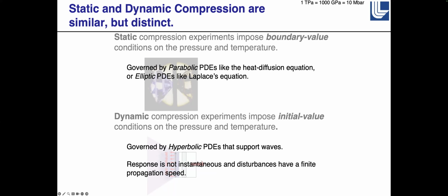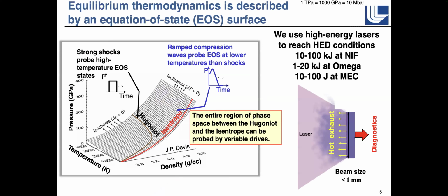So if you think about that, the types of partial differential equations that describe those, parabolic differential equations like the heat diffusion equation, are governed by boundary values, as are elliptic PDEs like Laplace's equation. So those are generally the types of equations that you're solving in static compression. In dynamic compression, the PDEs are hyperbolic, and hyperbolic PDEs support waves. Parabolic and elliptic do not. And so the response is not instantaneous. We have to wait for these waves to travel through our sample, and everything happens at a finite propagation speed. So measuring things like what happens as a function of time is critical to us. And nothing stays for very long in our experiments.